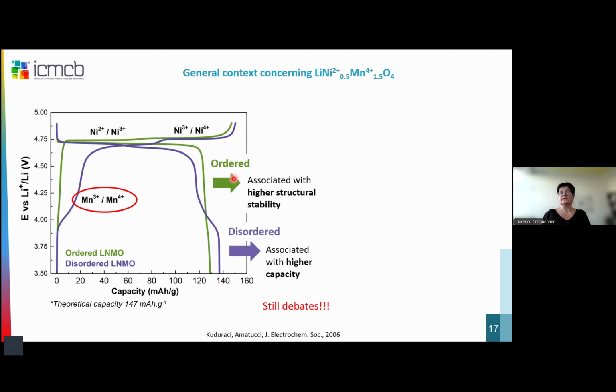So the ordered one, of course, is only a manganese 4 plus phase, when it is a perfectly ordered material. And in that case, it is associated with higher structural stability, because when we have manganese 3 plus, we always have problems with manganese 3 plus dissolution upon cycling, and the involvement of this manganese in the redox processes. On the other side, disordered is often presented as having higher capacity retention and higher C-rate ability due to this mixed valence we have between manganese 3 plus and manganese 4 plus. So still a lot of debates, and often the phase nickel 0.4, manganese 1.6 is presented as the best one, I would say.